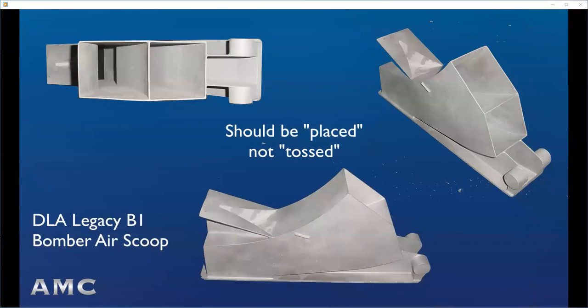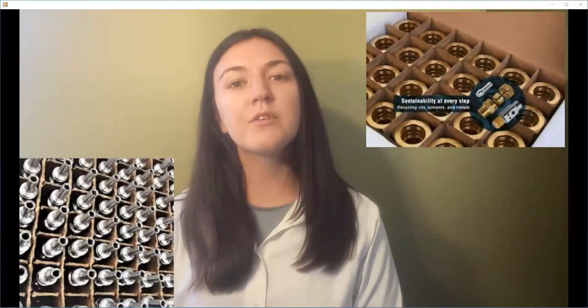The typical DLA legacy casting, especially airframe castings in aluminum, magnesium, and thin wall steels, need to be set up in the finishing process plans for placing, not tossing, as finishing processes are completed. It is also common to move high specification castings from one business partner location to another by truck. For example, from intermediate as-cast finishing steps at the casting facility to a local heat treat shop, or from the final as-cast finishing processes to a local coater or plater. For castings with thin wall projected features, it is important to package them with separators for the transit back and forth to avoid dings and distortion.